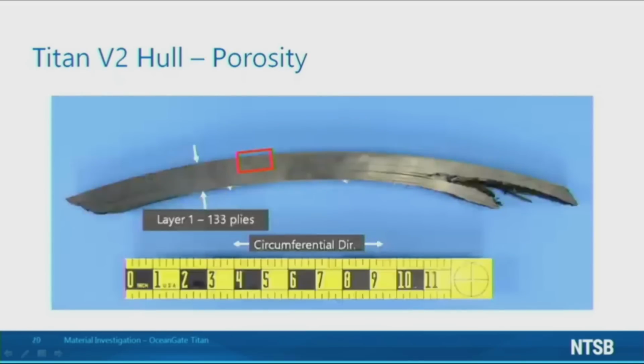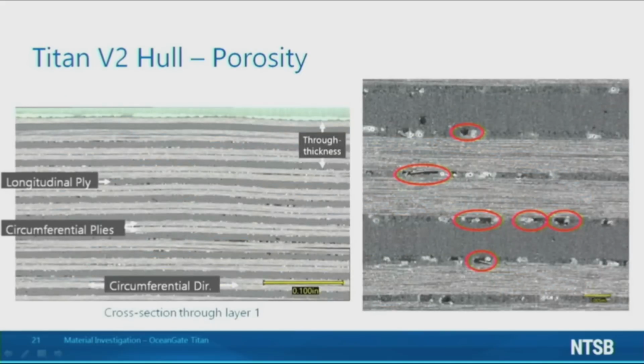Here's a macro scale image of the cut piece. The next slide is at higher magnification and shows the composite plies in greater detail. The higher magnification images reveal the laminate structure of the hull. The lighter gray layers are circumferential plies, where the fibers lie within the slide, and the darker gray layers are longitudinal plies, where the fibers run in and out of the slide.